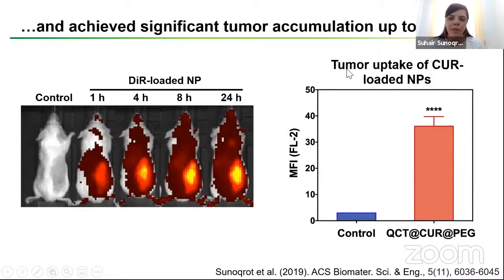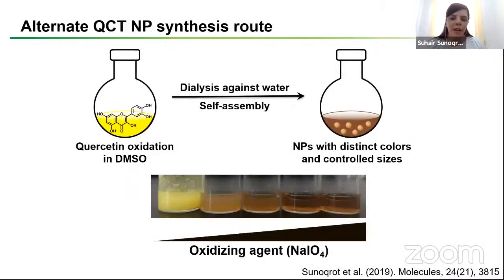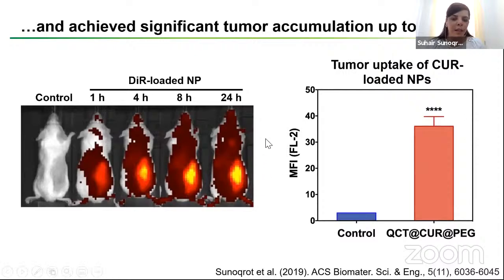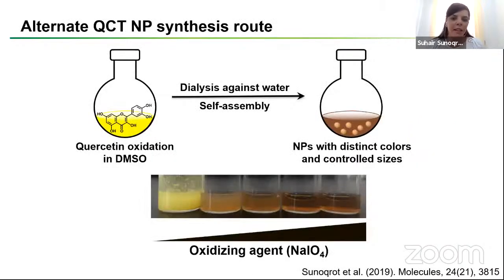And we also injected the animals with the curcumin nanoparticles and, after 24 hours, we measured the fluorescence of curcumin in the tumor tissues, and we found that it was significantly higher than the control, meaning that it was able to reach the tumors and accumulate there by passive targeting. So this was performed at King's College London, Khulud Al-Jamal's lab, where she specializes in the preclinical evaluation of different types of nanomedicines.